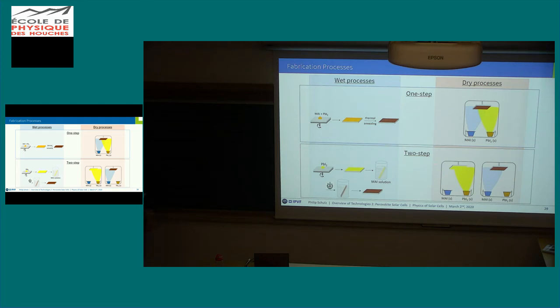The two-step process: here we first make a film by PbI2 evaporation and then dip it into a solution of MAI, for instance, and see the conversion into the perovskite film afterwards. Usually the penetration and formation of this film is not as good. You can see a lot of the PbI2 precursor remaining in the film, which is not necessarily a bad thing, but needs to be regarded as an issue that you have to deal with. And similar holds for the one-step process. Again, if you want to know more about this, ask Alex.